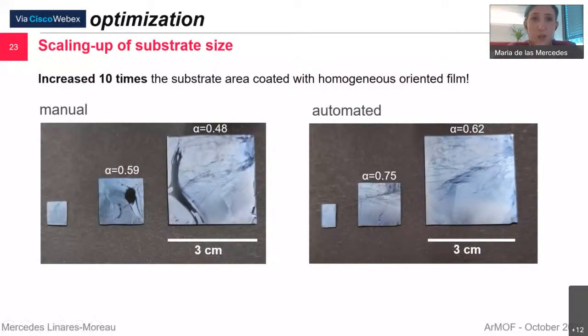Importantly, this also allowed us to increase the substrate size that we could coat. I think this is, for me, one of the most important conclusions: we were able to improve substantially the reproducibility and the coated area. Initially we were working with 1 centimeter by 1 centimeter substrates, and we were finally able to improve this up to 3.2 by 3.2. So these are the largest wafers that we could cover with a good homogeneity and orientation degree.